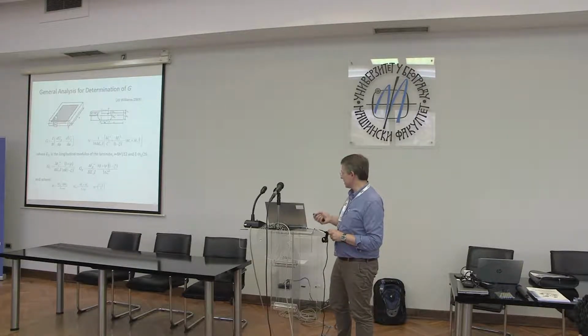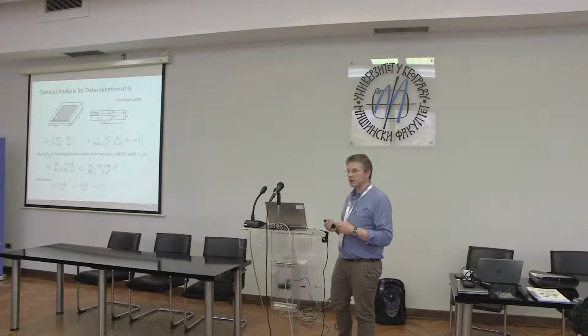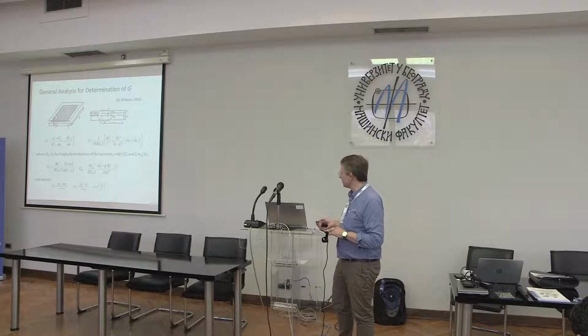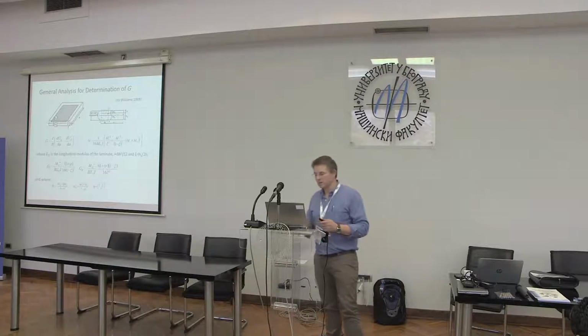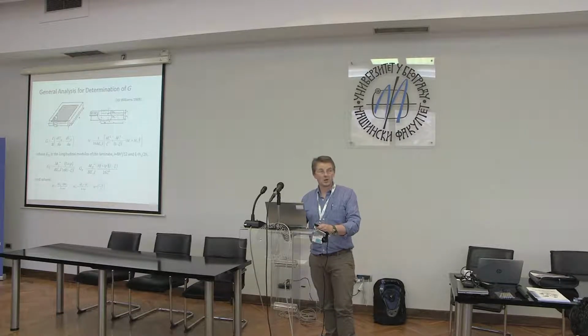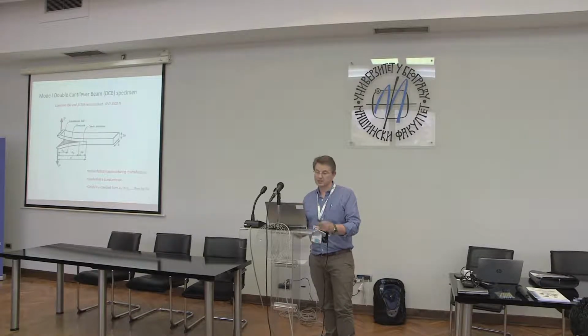And of course, the definition of G is the rate of change of the external work with respect to crack length minus the strain energy with respect to crack length. So, of course, if you don't have kinetic and other dissipated energy terms, you can determine your energy release rate. And that came down through the bending moments. And this was used to derive a whole set of equations for mode 1, for mode 2, and for mixed mode fracture in these laminates.